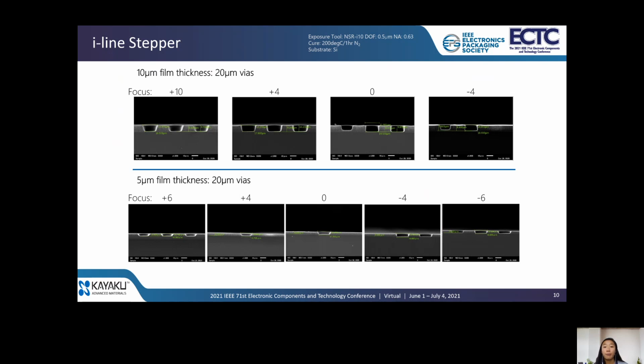PRL 29 samples were patterned with a 4 micron focus offset step from -4 micron to +14 micron, and hard cured to achieve around a 5 micron and 10 micron film thickness. We observed the 20 micron via profiles under SEM, and that's what's shown here. At a 0 micron focus offset for a 10 micron film thickness, we achieve straight sidewalls. With the positive focus offset, the profile begins to show a positive slope, which is desirable for minimizing stresses in the device stack and to ensure a uniform RDL deposition. At a negative focus offset, the 10 micron film sample begins to develop an inverted slope, which would result in gaps in the metal layer. This would be undesirable.